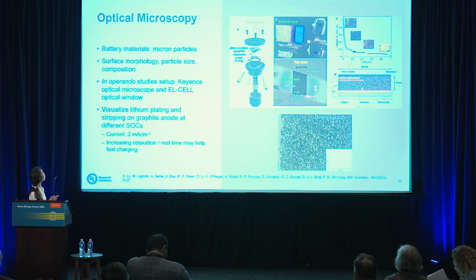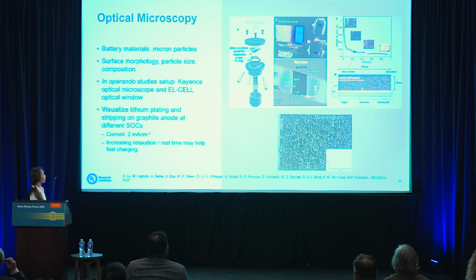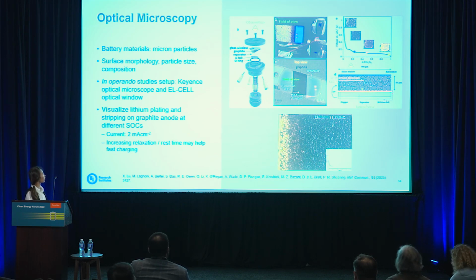They use a Keyence optical microscope over here, and it's paired with an EL-CELL optical window. As I mentioned, it's a good tool to visualize lithium plating and stripping, and there is a nice little video over here that I can play. The authors use a current density of 2 milliamps per cm squared, and with charging, you can see that there is this front that moves with charging. It's really a good tool to see what's happening in your batteries.